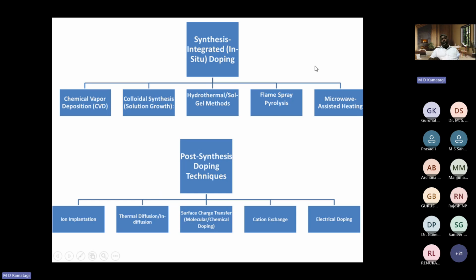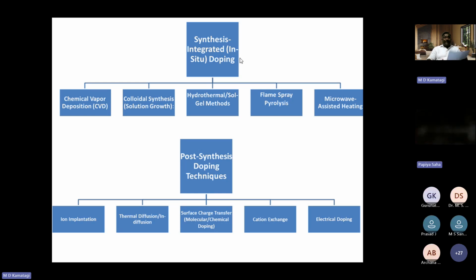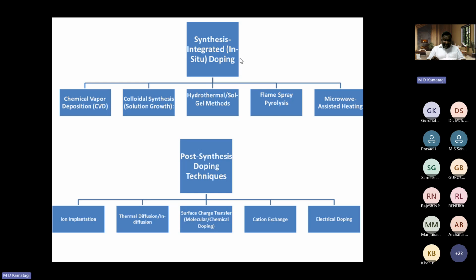There are broadly two ways to dope the material. One is in situ doping, another is post-synthesis doping. In situ doping has again subsections. Chemical vapor deposition is a common method, especially for nanowires and 2D materials like graphene, where the precursor gases containing the dopant atoms are flowed into the reaction chamber during material synthesis. Doping concentration and the location can be controlled by adjusting the gas flow rates and temperature.